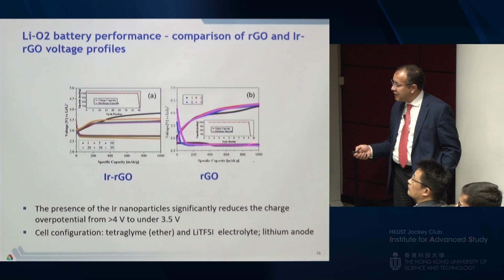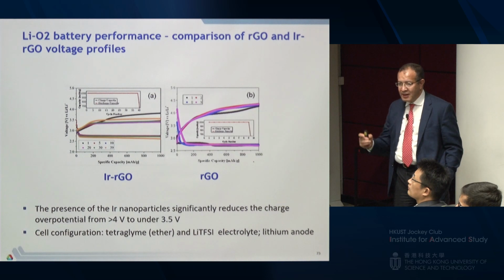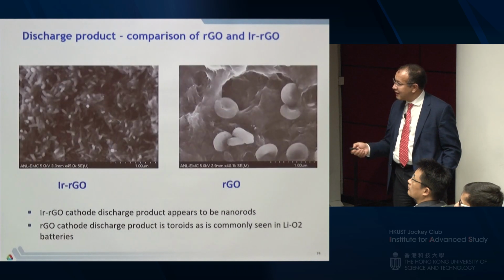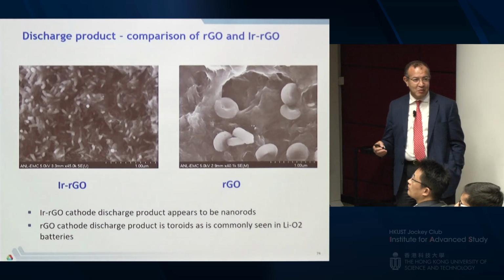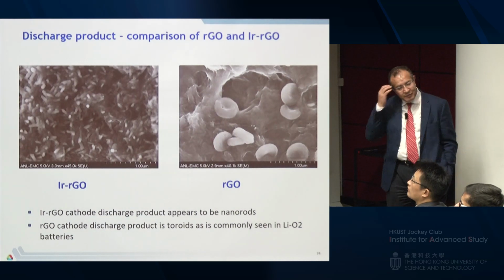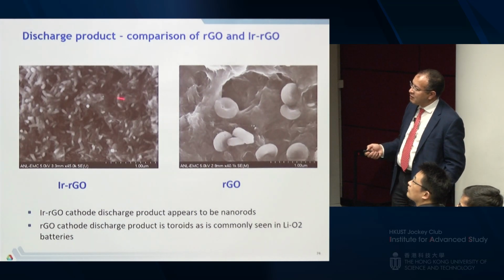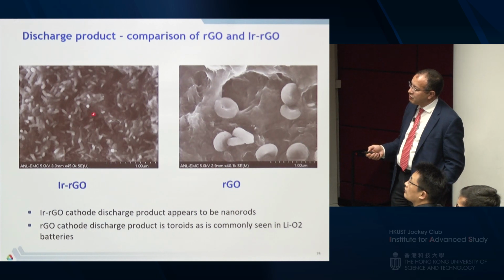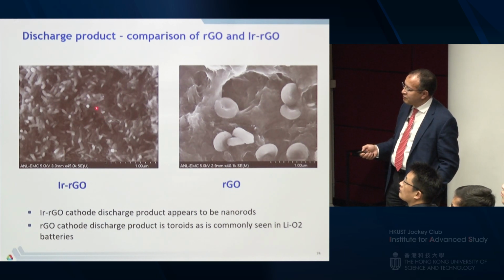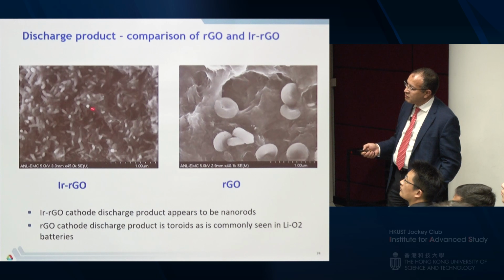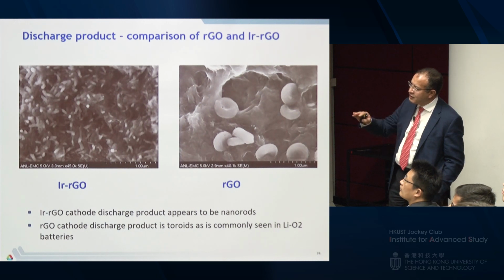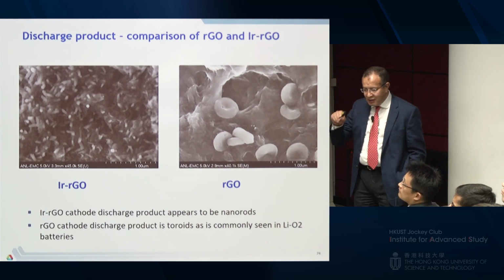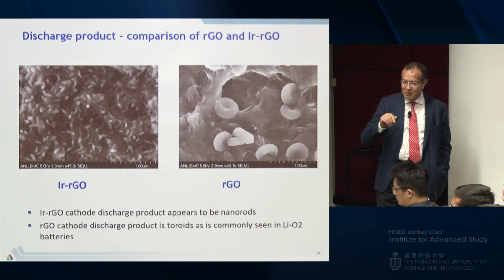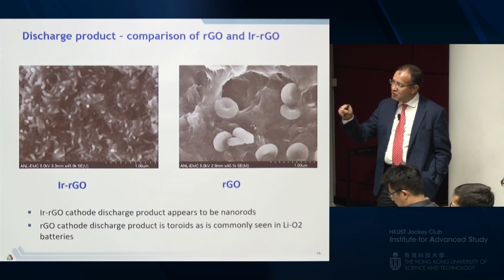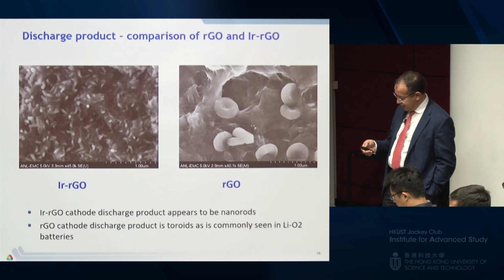Because in the lithium-air, the lithium peroxide has a donut-type shape, like this. That's what you've seen in most of the publications. But in our case, we've seen a totally different morphology. These are basically nanorods, very small nanorods, and highly dispersed. But they are actually very close to the catalyst. When we look by TEM, we've seen most of them are basically built on the top of the catalyst, which